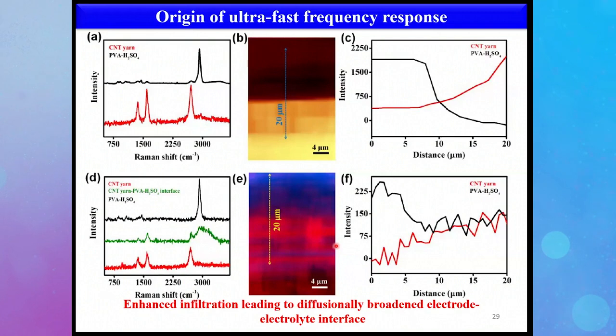Ayan Sarkar from ICER: would you tell me how the not annealed capacitor was behaving like a resistor, and how you anneal? When you have a capacitor and expose it to very high scan rates, there is complete breakdown of the double layer, so it essentially behaves like a resistor. The C part of the RC circuit completely drops off, leaving behind the resistor, and that's why you get a linear, ohmic kind of behavior. Whereas for the annealed device, there is still a cyclic voltammogram with a symmetric and supercapacitive nature, and that's why we think it's a supercapacitor, happening because of the reasons I discussed during my talk.